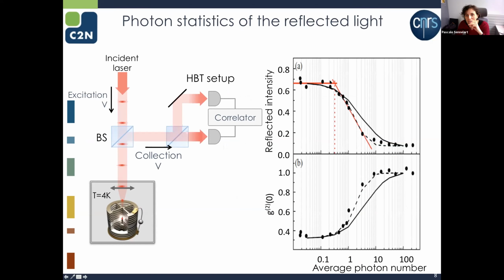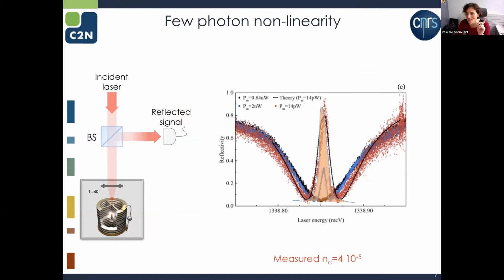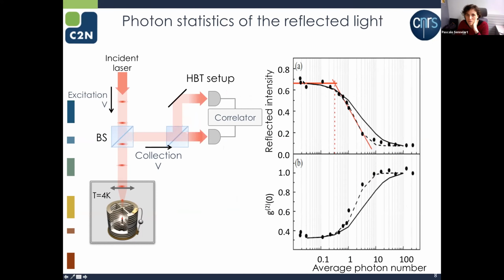And you see here that we go from a reflectivity above 65%. So it's no longer 90% as just before. And the reason is clear. It was a peak reflectivity. Now I'm sending a pulse. It has a width. So I'm integrating the pulse area over the reflectivity curve here. So it's still very high, around 65%. And when I increase the number of photons in my pulse, the quantum dot transition saturates, and I end up with a low reflectivity.